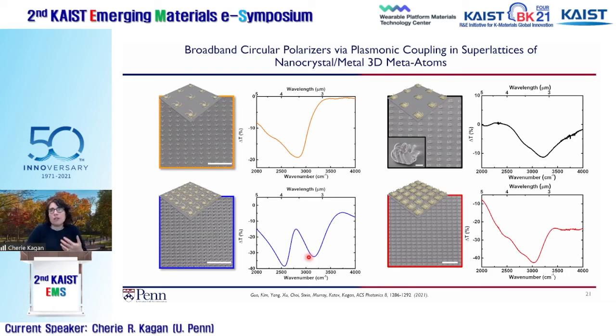And if we really wanted to make a broadband surface, what we did is we combined systems where we put lots of different arms. You can see there are 12 arms. There are actually four sets of three, where each of the four sets has a different length. And so that adds to the breadth of the response. And then we bring them close together, and so we get a large and fairly broad chiral response.